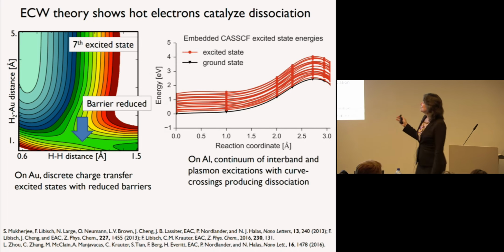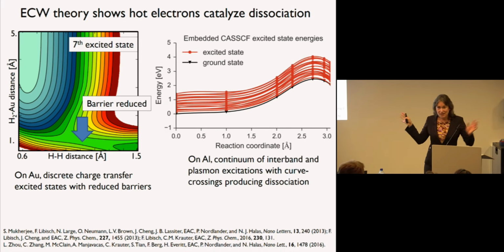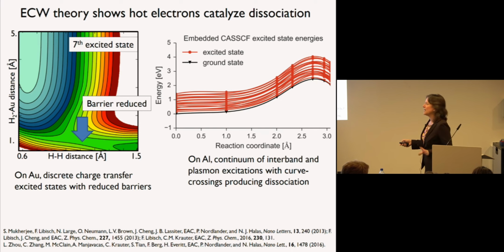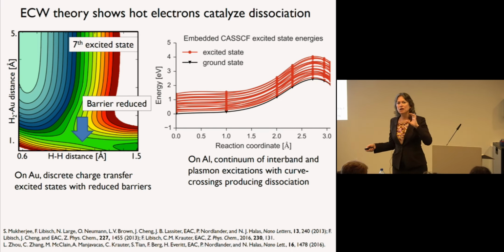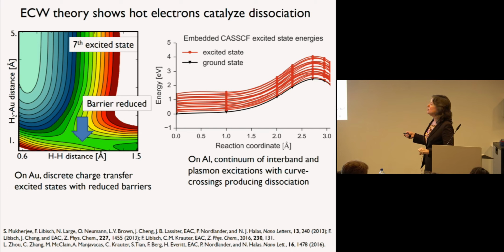And then this is showing you what happens on aluminum, just another case that actually they looked at as well, a different paper. And it's showing a different representation because I want to show you that on aluminum, unlike having a set of discrete excited states on gold, which is understandable because of the surface projected band gap that is known to exist on gold surfaces, on aluminum, which is a free electron-like metal, you get a continuum of excited states. And this is showing, it's marching along the actual minimum energy path, the ground state minimum energy path that's shown in black. So that's why you're seeing a one-dimensional coordinate here.